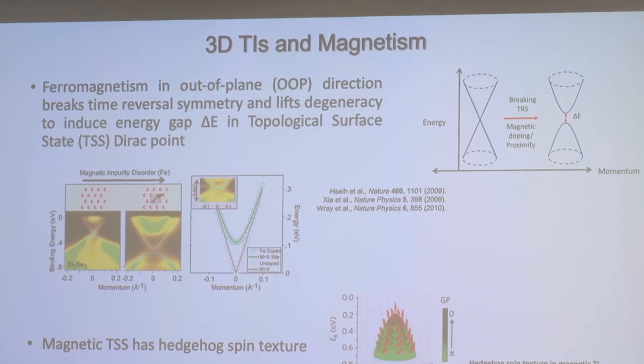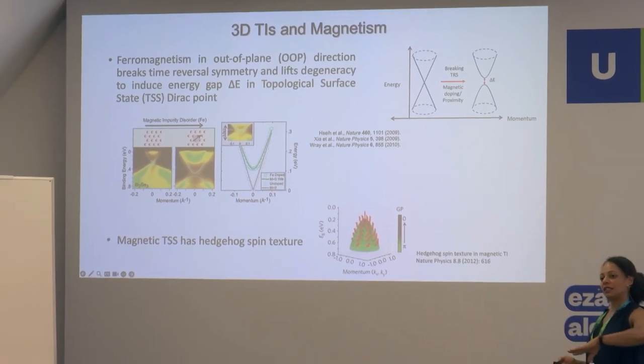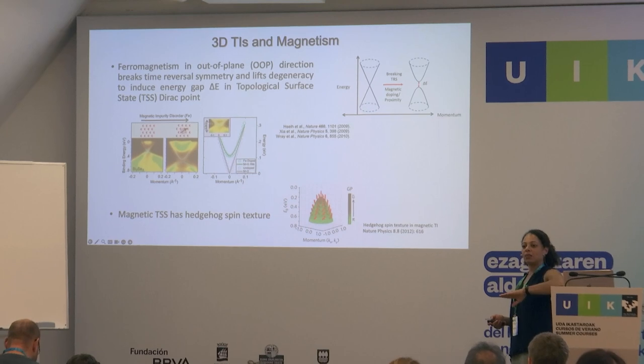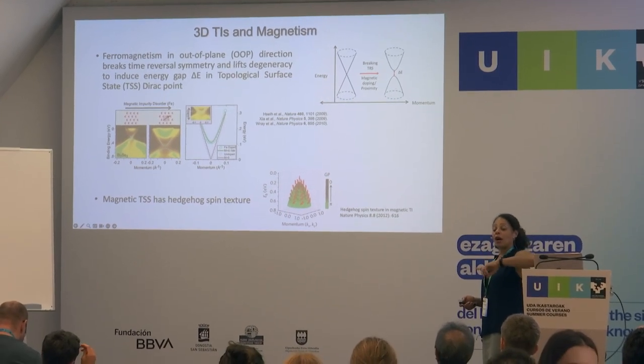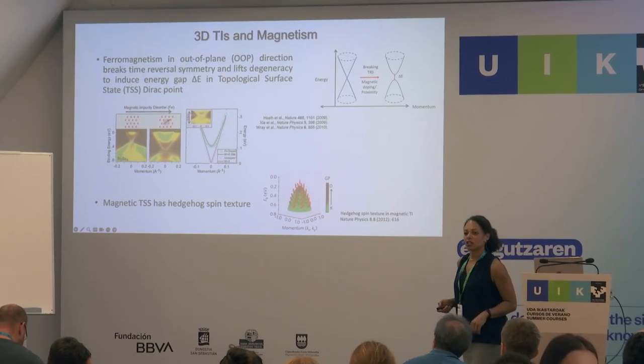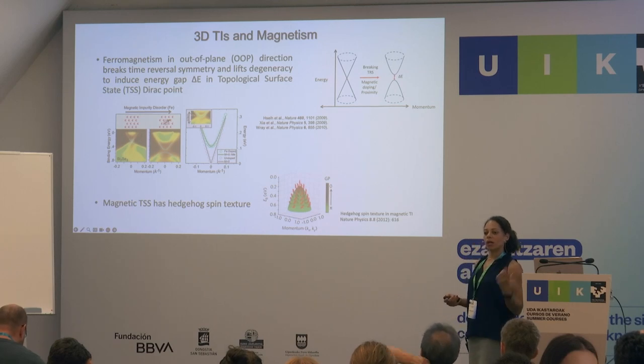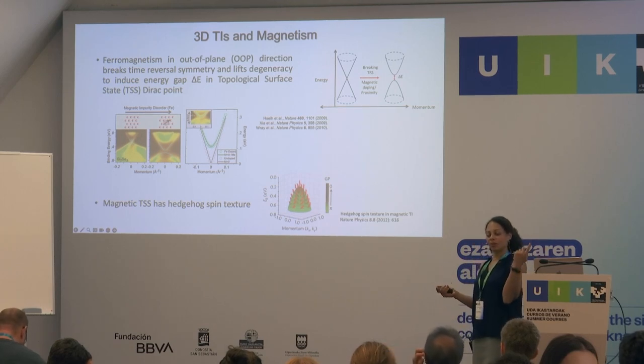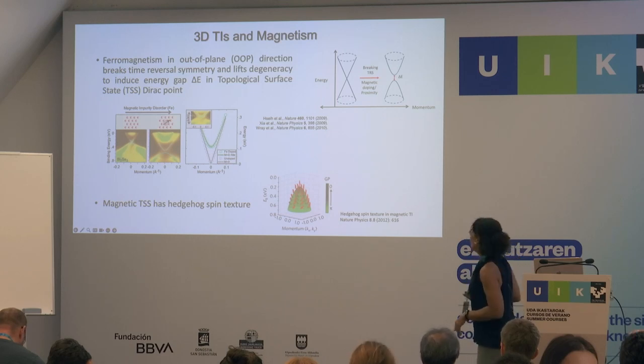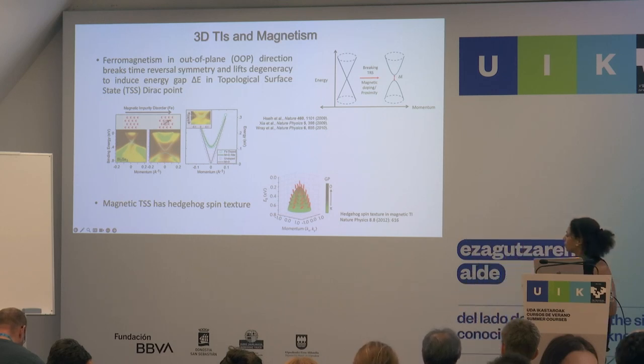I also want to note, as I said, that because of mostly this warping effect, the magnetic topological surface state has a hedgehog-like spin texture. And this is interesting because even though it's a surface state, you would think that the magnetism would lie in plane, but you do have components that go out of plane on the surface of a topological insulator, which again makes it couple well. You can then manipulate that. You can, with the magnetic field, tune the magnetic moment in and out of plane, depending on the sort of studies that you're trying to do.